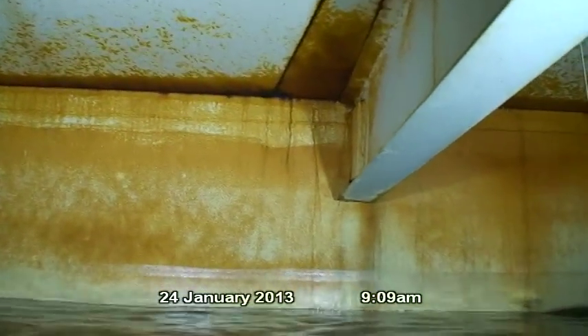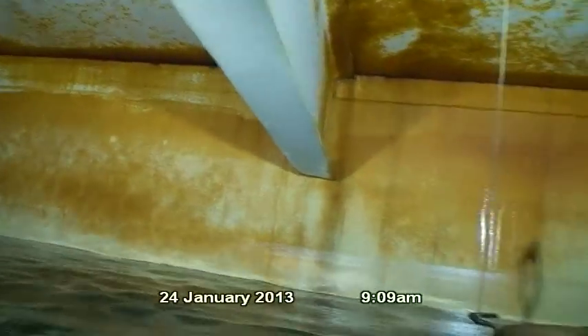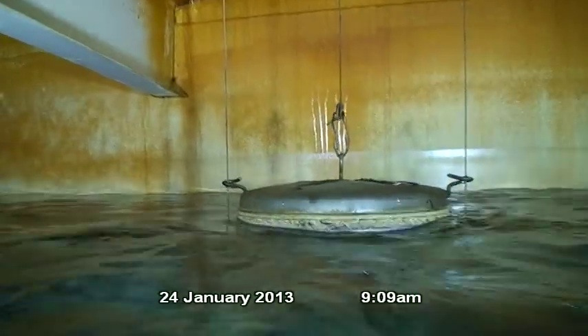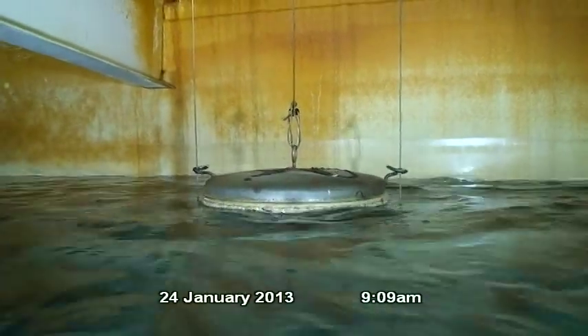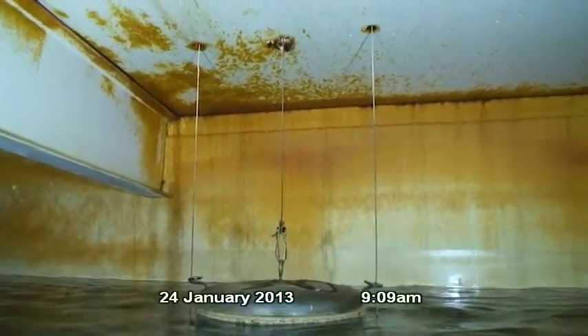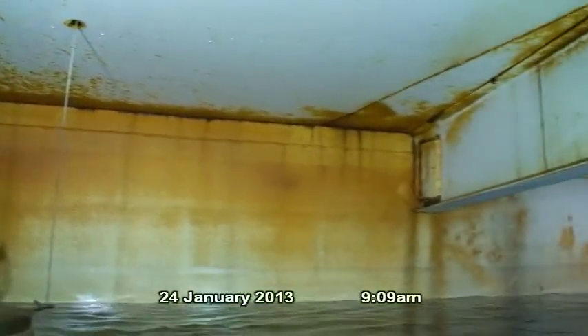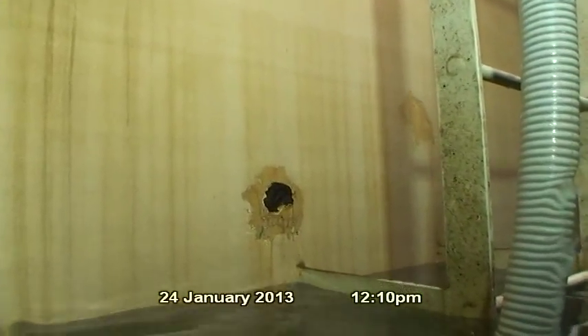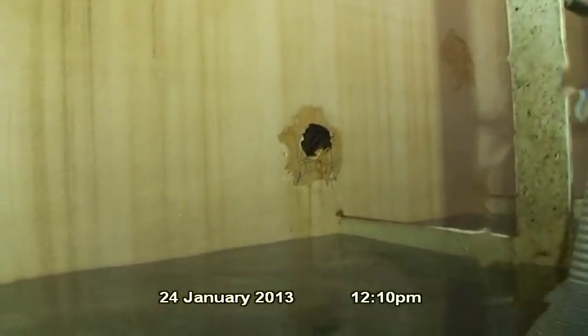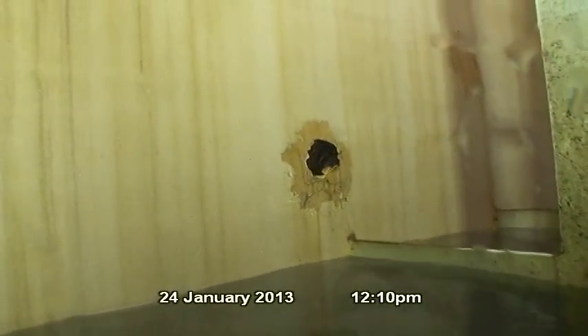All rafters appear to be securely welded to rafter clips. The float for the target is also in good condition and securely attached to all 3 wires. An area of dense corrosion and moderate to severe metal loss is located on the shell directly behind the interior access ladder. Aquatic Inspections would recommend addressing this area.